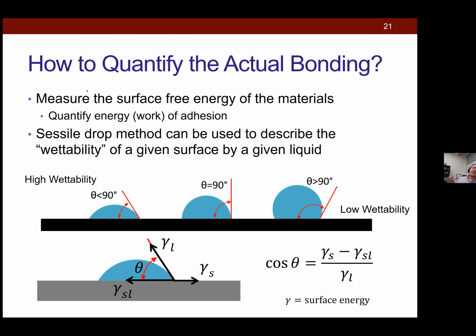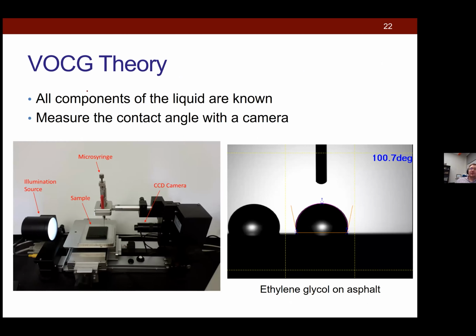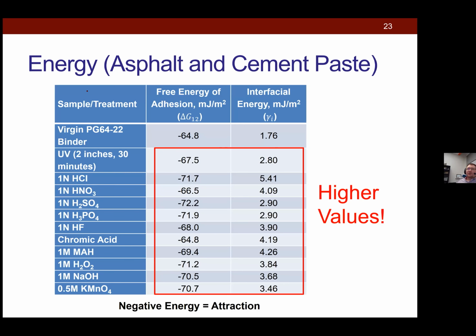And then we started looking at the actual sort of bonding energy between the asphalt and the cement. All right, and so here we're looking at the surface free energy using the sessile drop method. This was actually one of Alcadi's students doing this work at the time, and so that's how we kind of got into this to see if we could apply it to this study as well. So there might be people at Illinois still doing this type of work. I don't know, but here's the camera that's at A-Trail. We basically had the sample of asphalt. You put these different drops on it. You measure the shape properties of that drop, and you're eventually able to then calculate these sort of free energies of adhesion. You can calculate energies of cohesion as well. Calculate some interfacial energy.